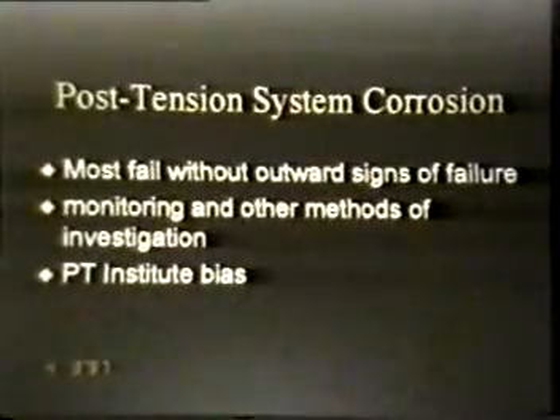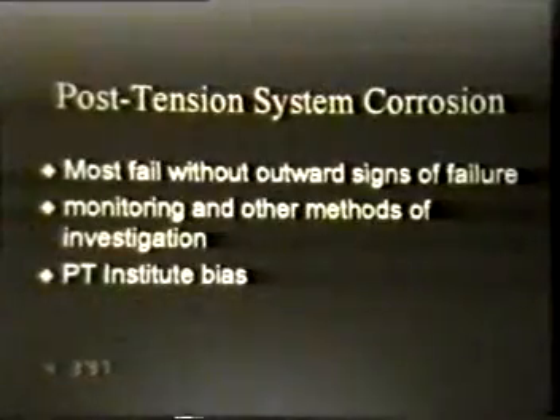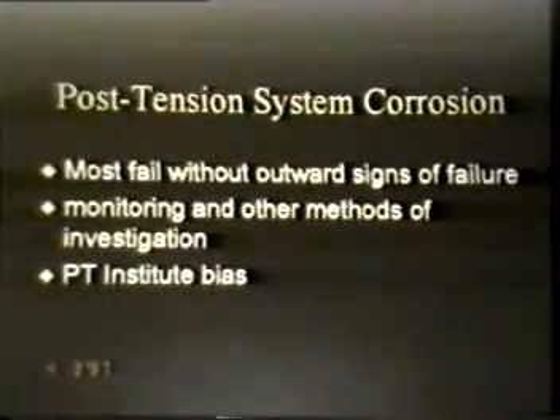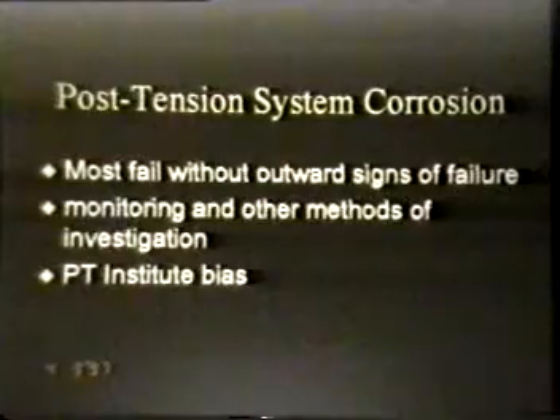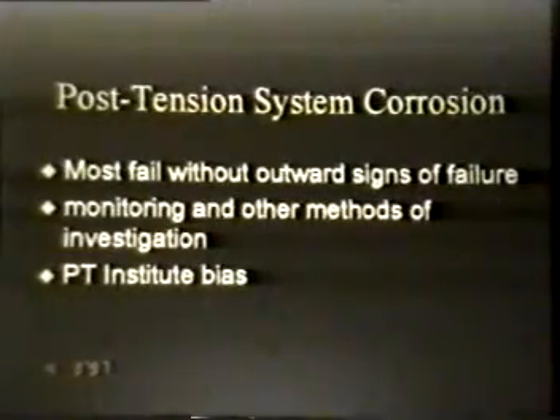But one of the things that we have found is that with these systems, what we thought originally was that there'd be telltales. When these cables broke because of corrosion, they would fly out of the slab. You'd see these big protrusions, cables and things hanging out of the slab. And we said, oh, that's good. We know when they're failing. But what we have found over the last couple of years is that most failures have no telltale. They don't show themselves. They just break.